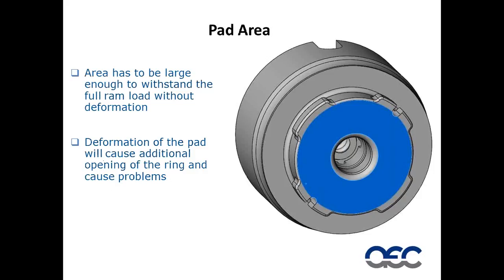The pad area is also very, very important. As the pad area changes or becomes deformed, it changes the amount of expansion in our dummy block. So if we go back a couple of slides and take a look at a 25-degree angle, we would have a 40 thou gap between the back of the mandrel and the pad area. But if the pad area is under too much pressure and actually is moved or deformed by 10 thou, at that point our gap will be increased to 50 thou and our expansion will go over 40 thou, which means that the dummy block will be prematurely sealing on the liner and we can't get rid of the gas entrapment.